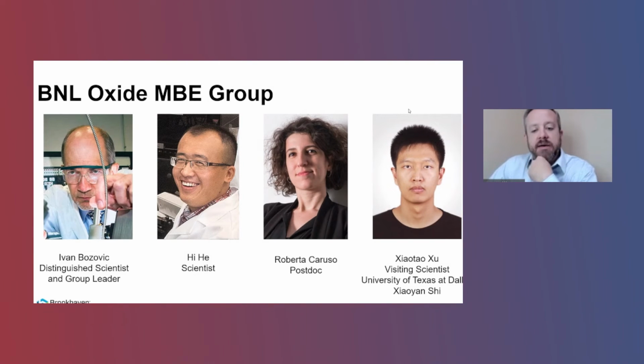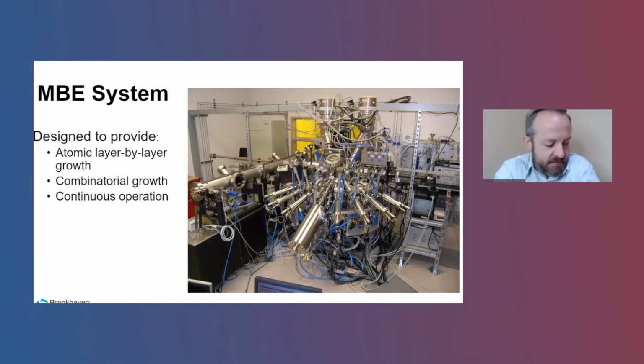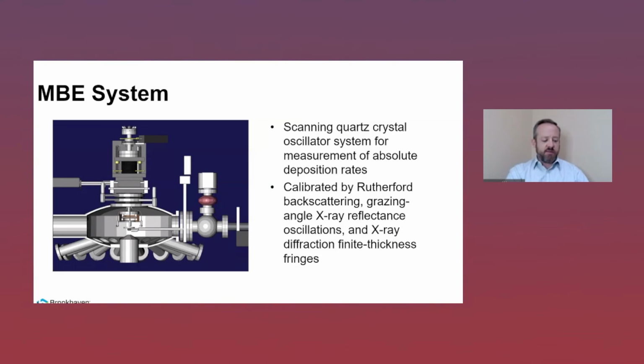So as the name would imply, oxide molecular beam epitaxy, we synthesize thin films by molecular beam epitaxy. This is our MBE machine at Brookhaven, which I think you've probably seen a few pictures of already today. Xiao Tao gave a real nice overview describing how the films are grown, so I won't go into too many of those details, but just in case you missed his talk, I did just briefly want to point out that this system was designed for atomic layer by layer growth, as well as combinatorial growth and continuous operation. The chamber has space for 16 sources, and each of these sources is calibrated by a quartz crystal monitor before each growth to determine absolute deposition rates, which in turn are calibrated by Rutherford backscattering and other techniques.